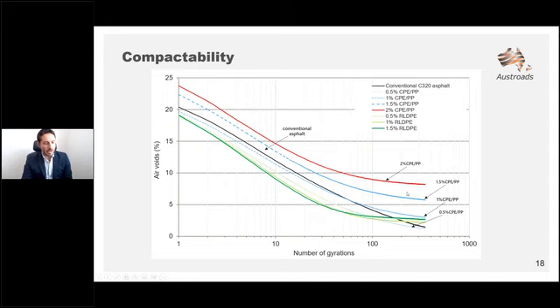I will show you a video in a second. But depending on the type of plastics, you may have 2 different behaviors. So if you look at the green curves here in this graph, they were quite easy to compact up until a certain point where the curve will start becoming a bit horizontal. So you really need a little bit of extra energy to make sure that the void content goes down. But actually, we found that they were quite compactable when we were using the RLDPE, so the post-industrial type of polymer. When using CPEPP, because of the polypropylene content and the higher melting point of polypropylene at around 160 degrees, that will probably be tough to compact compared to the other.